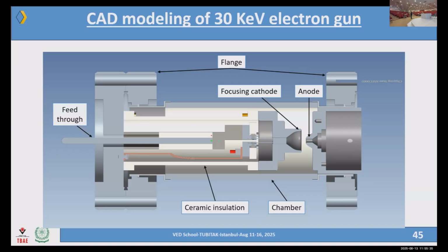Number one, you should have insulation between anode and cathode. Insulation means that you have to operate it at 30 keV or 50 keV, maybe 100, 200, 300 even. So that insulation comes from materials. That material usually is ceramic in our case. Why ceramic? Because it is an insulator, of course, but also it is vacuum compatible. We are not free to use any material that can be an insulator. Vacuum compatibility is perhaps the most important criterion when it comes to the selection of materials.